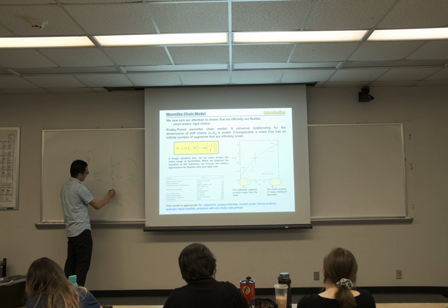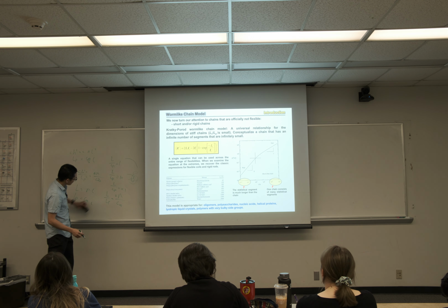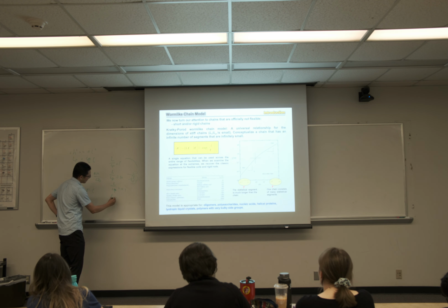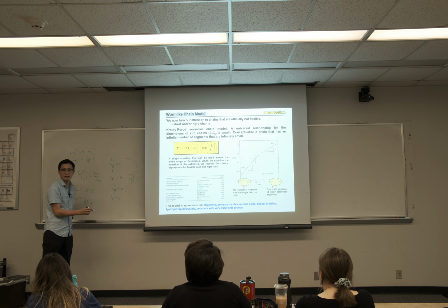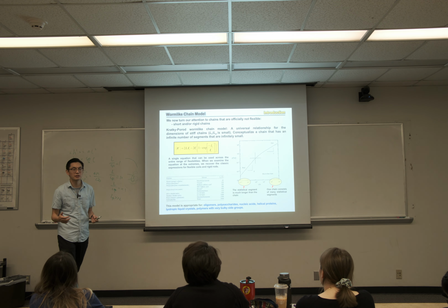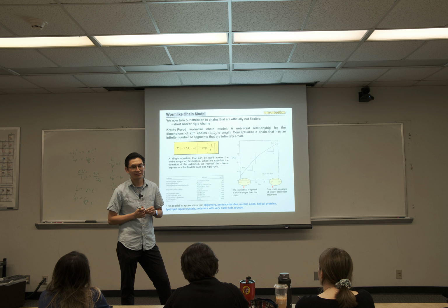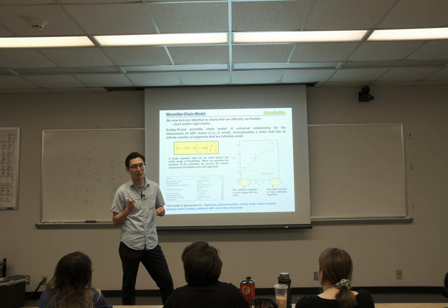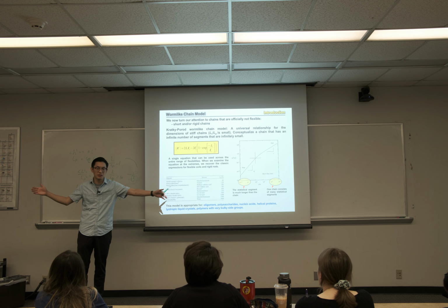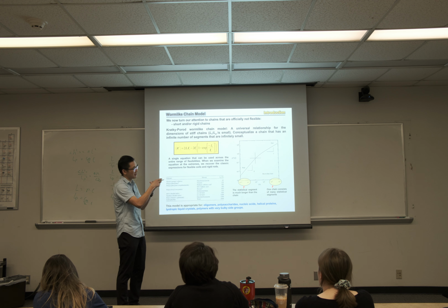If L divided by LP is equal to 0.1, that means your LP is much, much bigger than L, so your persistence length is bigger than L. In what scenario do you have a persistence length larger than the chain? Really short chains, or a rod-like chain, like a piece of rod. So this would have a persistence length longer than the chain.